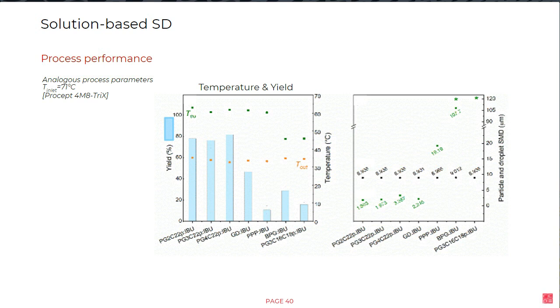In the other figure, we have the initial droplet size after atomization, and the particle size of the product at the outlet. So we are comparing these two to provide, let's say, a quantitative idea of the agglomeration at the outlet. When the particle size is actually larger than the droplet size, we can have a sign of agglomeration in the system. Usually it's like that. Of course, there are some conditions in which larger, very low density particles are provided. This is not our case here. So this statement of particle size larger than droplet size will give us a sign of agglomeration.